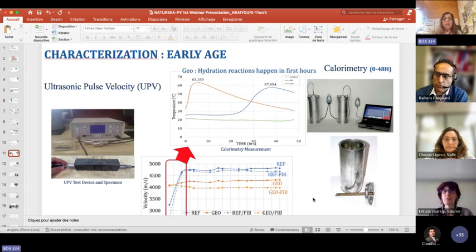Many tools, many devices in IDESEM in University of Bordeaux are used here. Something usual, which is calorimetry, which can just show the difference here. It's about heat. We can register temperature during hydration. During the first hours of hydration, we can see that geopolymer shows a lot of heat. The temperature is higher in the first hours compared to the reference one with cement, whose hydration reactions are delayed a little bit compared to geopolymer.